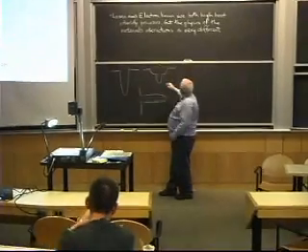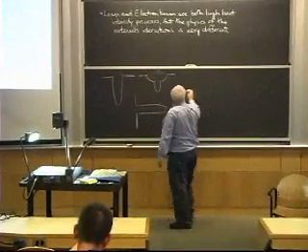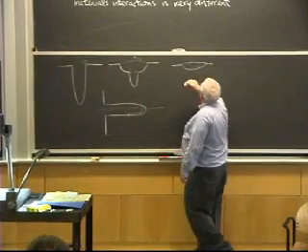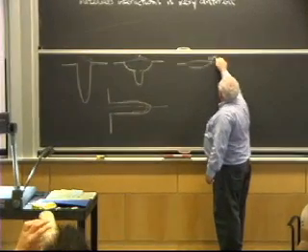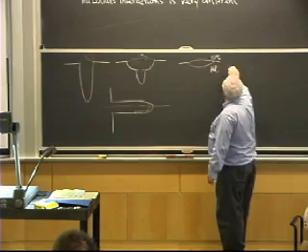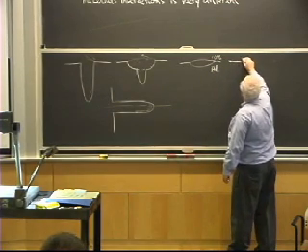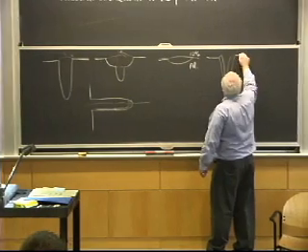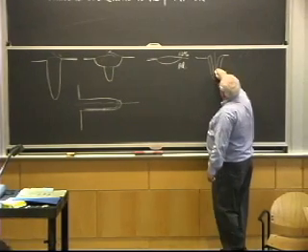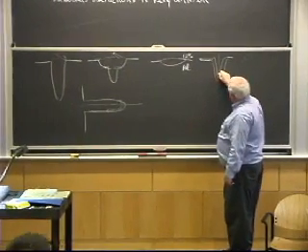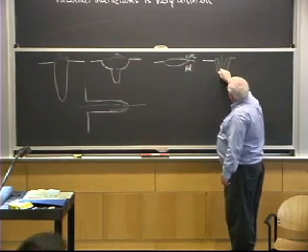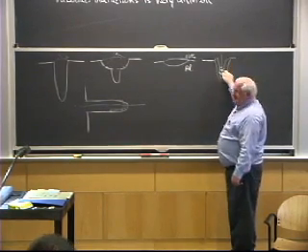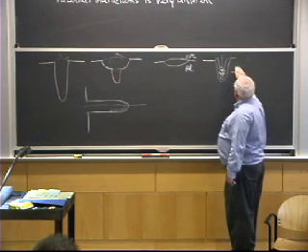90% is radiated away if I'm just melting on the surface. So if I have a situation where I have a weld pool like this, that's fairly shallow, I'll have 10% absorption if the base material is aluminum. On the other hand, if I put in enough power that I start drilling a hole like this, and the light gets down in here, it may be 10% absorption on this surface, but where does the light get reflected to? It gets reflected back inside here. And so the actual absorptivity inside the cavity starts approaching 100%.